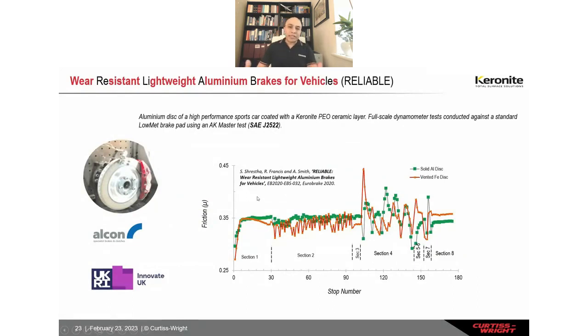So we thought, okay, let's give it a shot. We put a proposal to the UK government, and Innovate UK funded this project. What we did here is we tested a full-size aluminium brake disc for a mid-size high-performance car. We tested this with PEO coating, and we measured the friction coefficient and compared it with the existing technology, which is the grey cast iron brake disc.